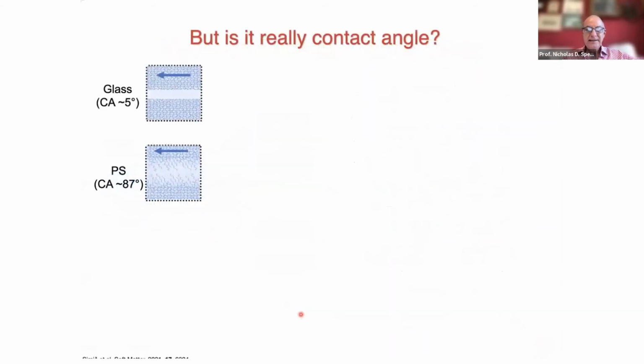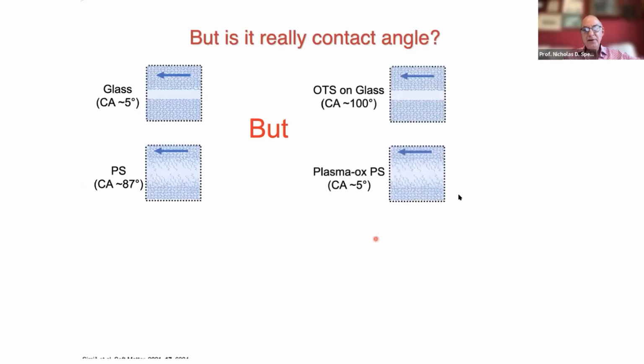Now, the question is: is it really contact angle? What first alerted us to this is we took glass and made it hydrophobic, and we took polystyrene and made it hydrophilic. The hydrophobic was OTS on glass, so silanes on glass. For hydrophilic, we used plasma. We find that this is exactly the same as the untreated polystyrene, and this is exactly the same as the untreated glass, although we've drastically changed the contact angles. So in other words, it's not really contact angle. It's not just hydrophobicity.